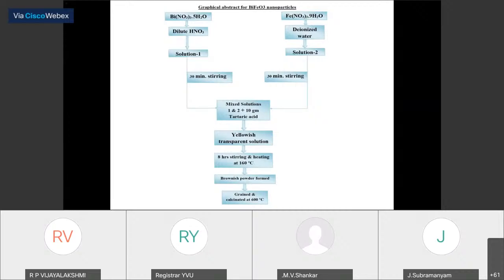We used both methods to synthesize bismuth ferrite oxide nanoparticles. What we noticed in the final product is that the bismuth ferrite oxide synthesized by chemical co-precipitation had mixed phases. We tried many times, but every time we got mixed phases in terms of the actual crystal structure. Then we switched the procedure from chemical precipitation to the sol-gel procedure, in which we added tartaric acid. In the final product we didn't notice any mixed phases after synthesizing the bismuth ferrite oxide by the sol-gel method.